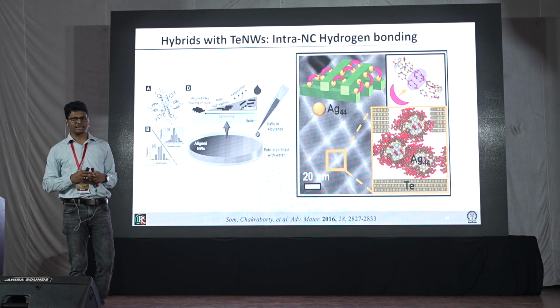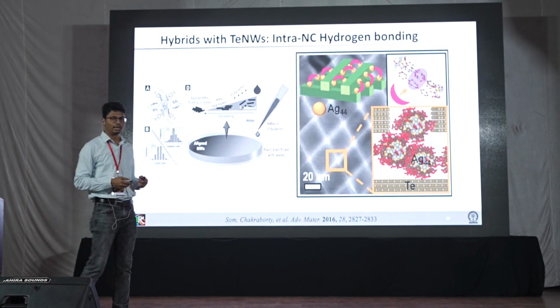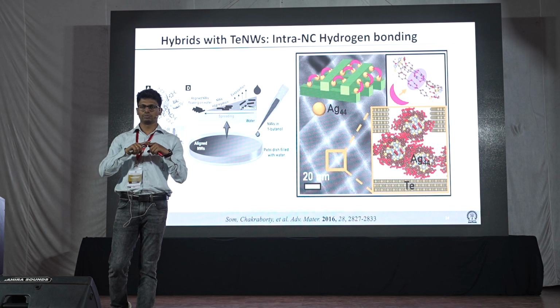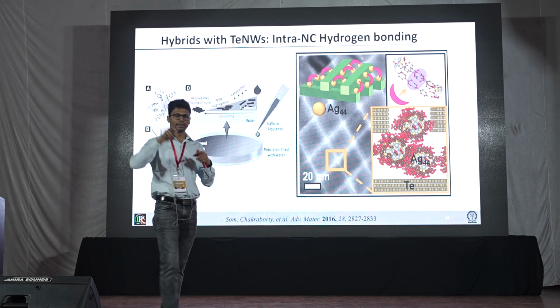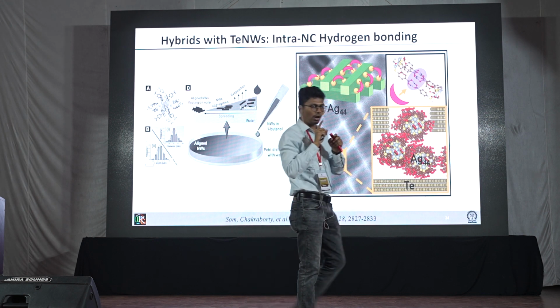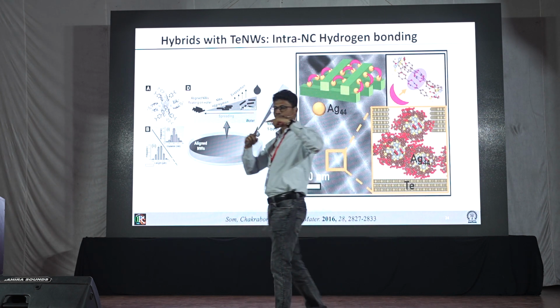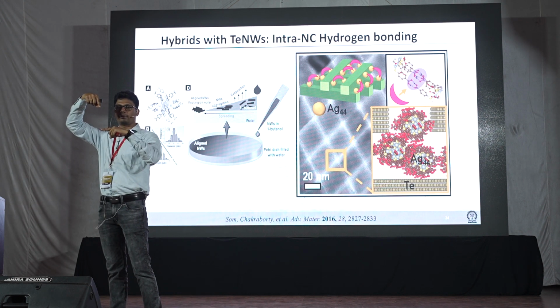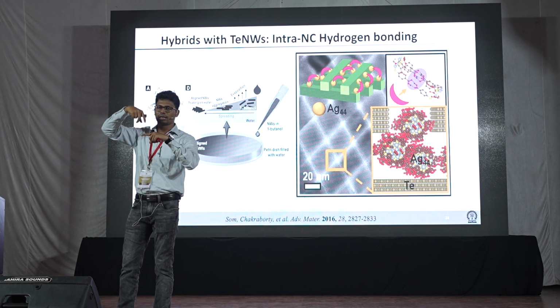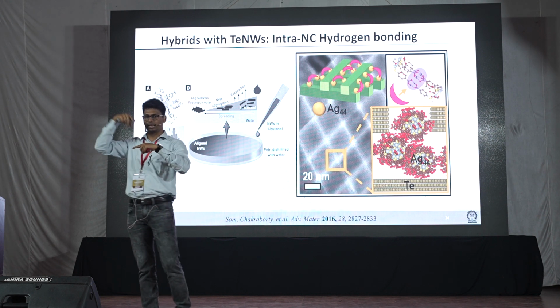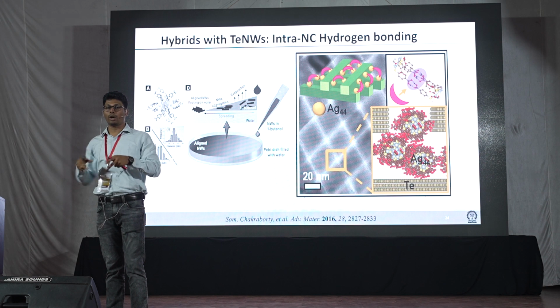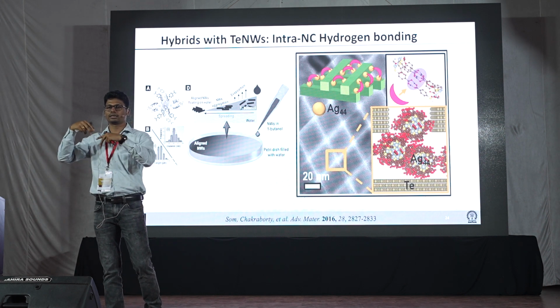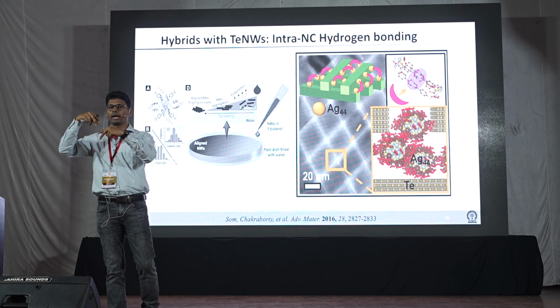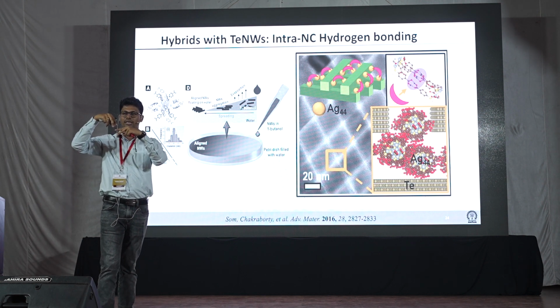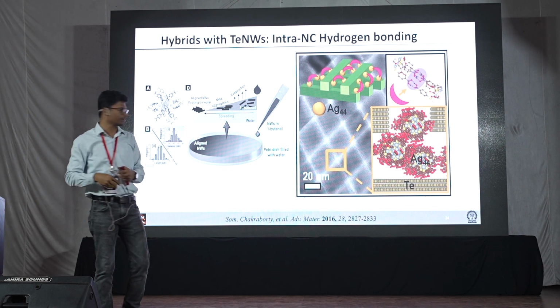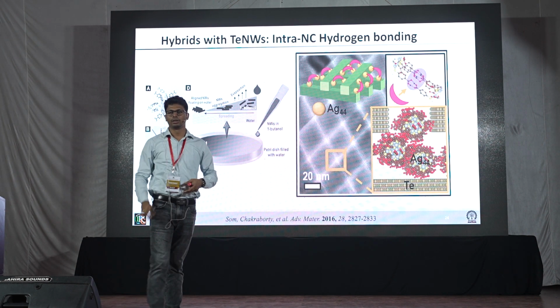And these crossed bilayers, we did several experiments, and from there we found out that this is because of inter-cluster hydrogen bonding. So clusters are sitting on top of tellurium nanowires, and the ligands, basically the mercaptobenzoic acid, the carboxyl part is anchoring on the outside, right? So when you have the other side, you also have a tellurium nanowire where clusters are sitting, mercaptobenzoic acids are there, and only at a specific angle of 76 degrees that happens. So we computationally probed why, and there is a larger number of hydrogen bonds, that is the most feasible way to get that kind of hydrogen bonding at a 76 degree angle, and that is why it is strongly stabilized, and we form big layers of bilayers.